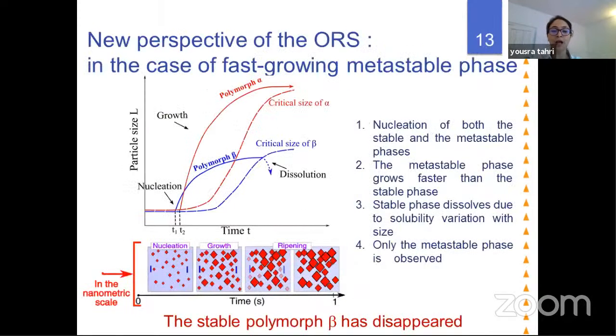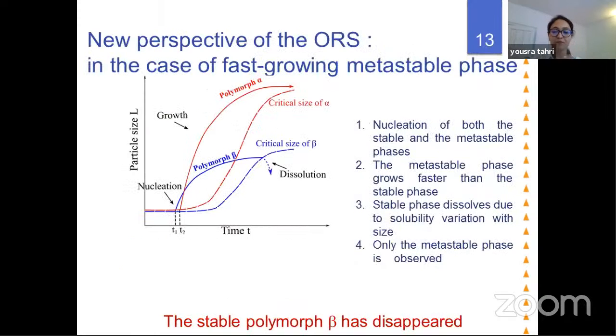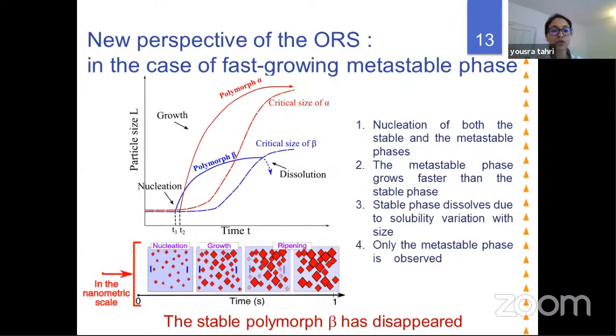So how can we explain this? Normally both polymorphs crystallize more or less at the same time. Then the alpha phase, which is a fast growing phase, will grow very fast and will consume supersaturation. The stable phase will also grow, but much more slowly. The supersaturation is consumed, the critical size of both polymorphs will increase, and at some point the stable phase will find itself undersaturated and will dissolve.